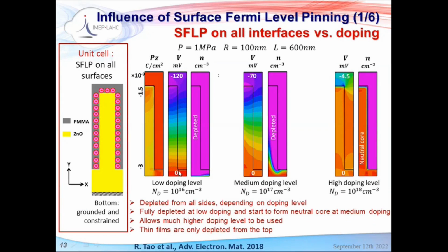This is the distribution of the potential. This is the distribution of electrons, of charges, in the 3 cases, basically. So for low doping concentrations, the nanowire is fully depleted, meaning that there are no free electrons. So there will be no screening, and you can obtain the maximum potential from the device.